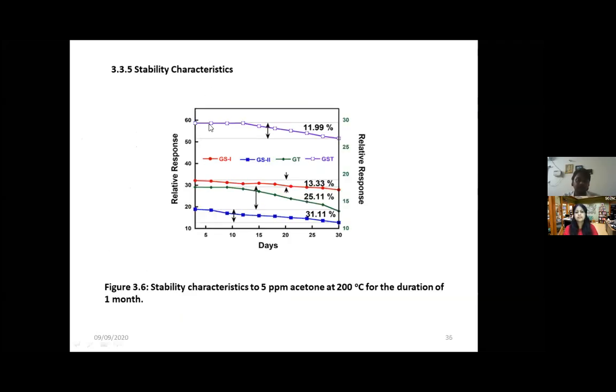And the next characteristic is stability. For the same 5 ppm acetone at 200 degrees Celsius, we checked the response under the same experimental conditions. We repeated at 5 day intervals for 30 days. And we observed a decline in response for all four sensors. This may be due to the harsh conditions it has been operated in. So there is a need to replace the sensor at least once in 2 weeks.